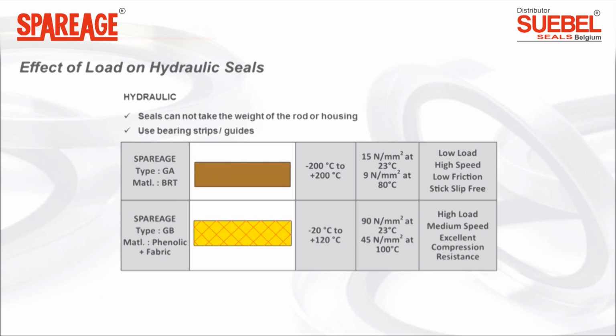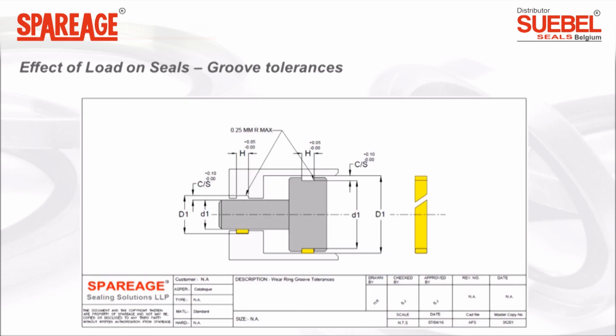The higher the temperature, the lower the load-bearing capacity. Bronze-filled Teflon wear rings are suitable for temperatures up to 200 degrees Celsius and have a load-bearing capacity of 9 to 15 Newton per square millimeter. Phenolic fabric wear rings have a high load-bearing capacity of up to 90 Newton per square millimeter at temperatures up to 120 degrees Celsius. Bearing rings have close groove tolerances. Please refer to the catalog for the same. If the tolerances are not maintained, the bearing rings will be rendered non-functional.